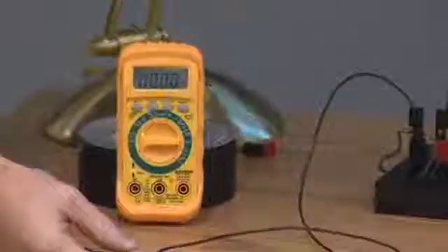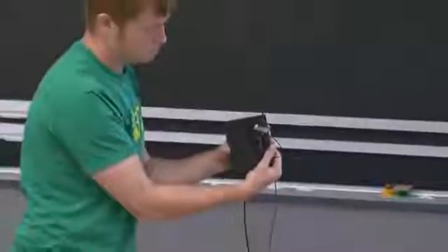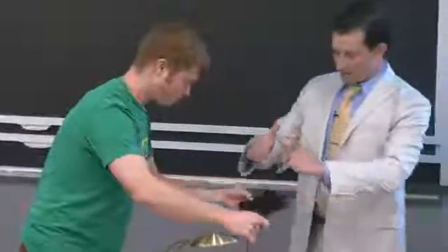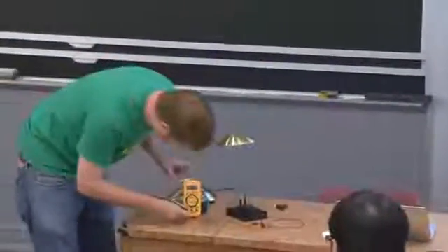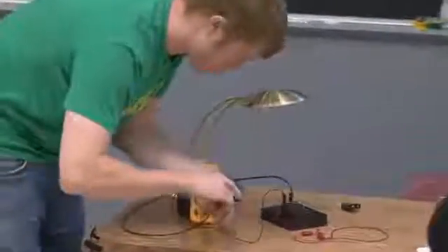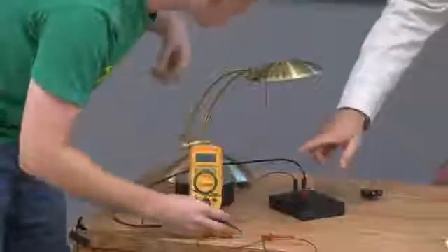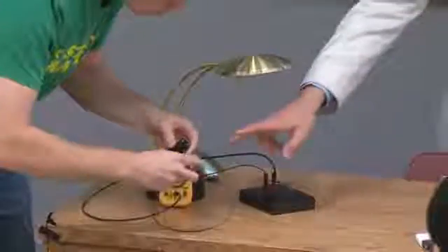Let me explain to you what we have right here. We have a bare piece of silicon and two electric leads on either side. So it's a bare piece of silicon, no device, just a piece of silicon. And we have electrical leads coming out of either side. We have a very low resistance contact on either end. For those who are curious, we used a mixture of indium and gallium. Soldering iron scratched the surface, penetrated the native surface oxide, and put the electrical leads on either side. And we have this connected in series here to our current readout device.